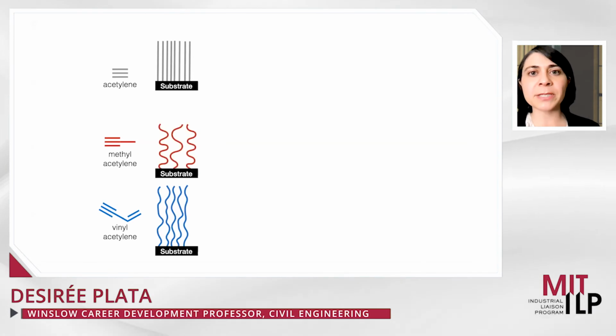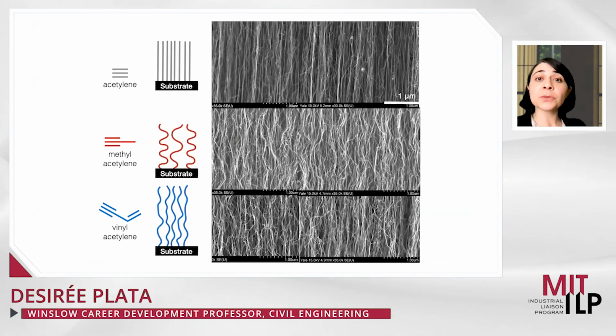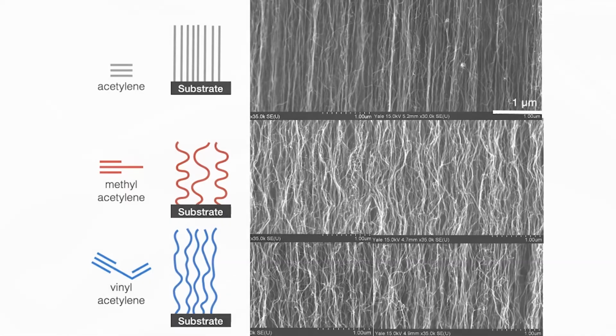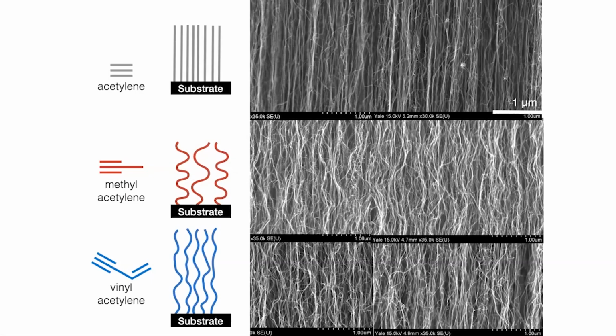So there's a cartoon representation of our hypothesis, and here's what it looked like under transmission electron microscopy. And now, depending on what you've put in your coffee this morning, you might say, yes, this is supported. We see very straight structures in the acetylene-fed growth, more tortuous or wavy structures in the methylacetylene-derived carbon nanotube forests, and something in between for the final vinyl acetylene forests.